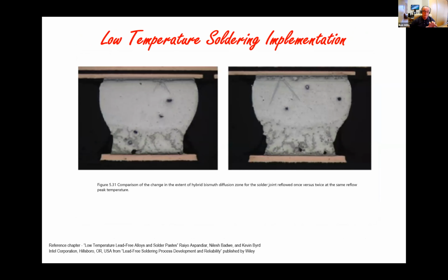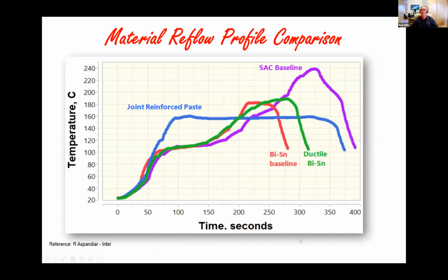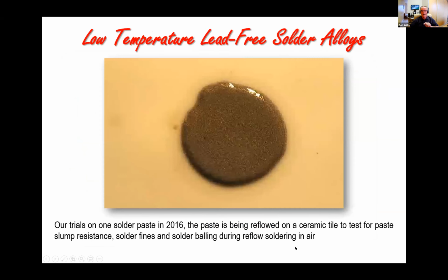These two photographs illustrate through a microsection the combination of the low temperature material into the SAC alloy, and come from one of the books that I illustrated earlier. So it gives you a feel for what's actually happening at a metallurgy level during the soldering process. Now, talking about the different technologies, these are some examples of profiles used as part of the iNEMI project, and it highlights the SAC reflow baseline. As you see here, you see two examples of low temperature materials, two varieties of materials, not to be specific about them, but it also mentions joint reinforcement paste. You can see that the profile in blue is quite different from the tin bismuth and bismuth tin alloys, which we'll highlight in a second.